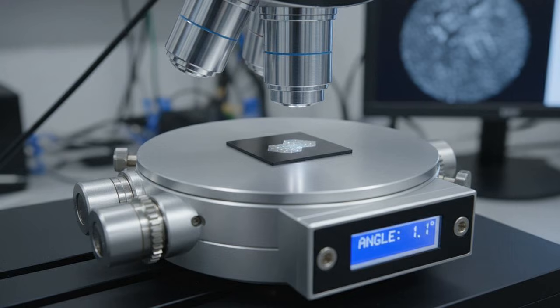Using a sticky polymer slide, they picked up only half of the flake. The graphene tore, leaving half on the bottom and half on the sticky slide. Because these two pieces came from the same crystal, their atoms were perfectly aligned. Then, they simply rotated the stage holding the bottom piece by exactly 1.1 degrees and lowered the top piece back down. This created twisted bilayer graphene.